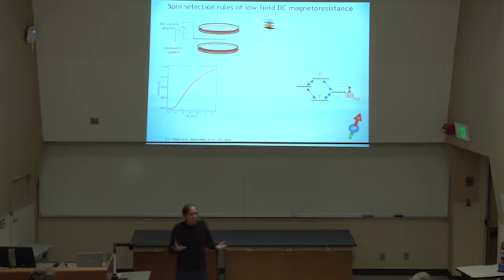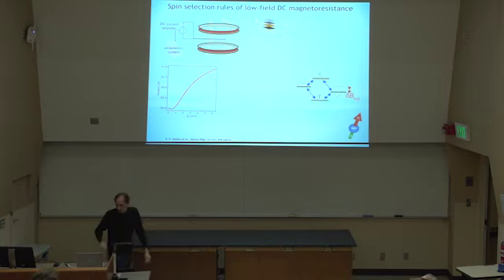Where do they come from? They come from the all-abundant hydrogen, because hydrogen nuclei have a magnetic moment, and every electronic state, these localized electronic states, only interact with a few hydrogen, and the net field of those, expectation value, is 0, but for any given state, it's somewhere between minus a millitesla and plus a millitesla, and you just have to outdo these fields in order to change the permutation symmetry within your charge carrier ensemble. And that's the whole trick.